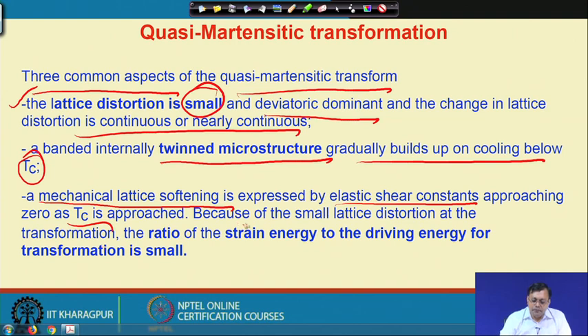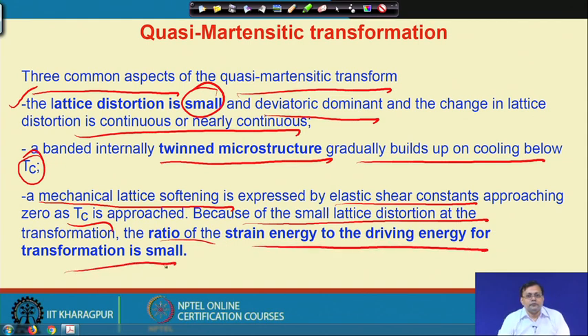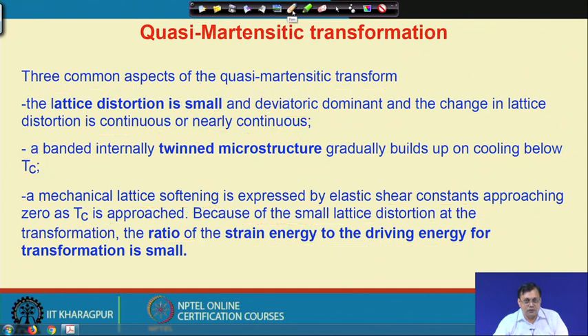However, because only a small lattice distortion is involved, the ratio of the strain energy to the driving energy of transformation is very small, and that is the reason, since this lattice distortion is small, the morphology is not dominated by that particular case.